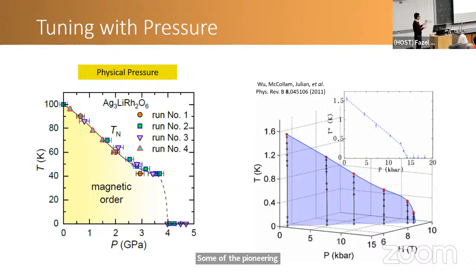And so, for example, when I was a PhD student, they were doing this very nice work. One of the PhD students in my group and a postdoc in my group, Alex McCollam, were basically looking at the suppression of magnetic ordering in a correlated metal, strontium ruthenate, as a function of pressure and field. These are non-thermal parameters. And eventually you can suppress the magnetic ordering, for example, by pressure or by magnetic field. And this point where you suppress that continuous transition is called a quantum critical point. So basically I wanted to do the same thing on this material. And my PhD was of course on pressure, so it made sense to do that.